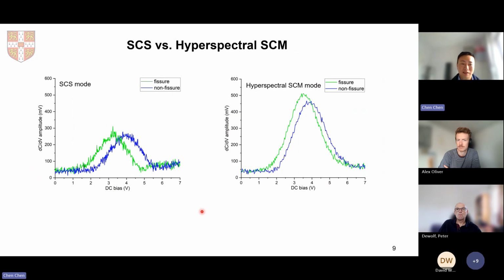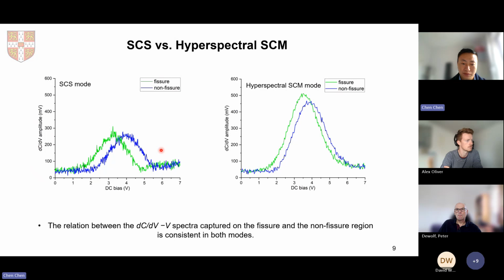We collected local dC/dV curves in two modes, SCS mode and also hyperspectral SCM mode. As you can see, in both cases, the fissure always shifts towards negative DC bias relative to the non-fissure curve. The relation between these two spectra, captured on the fissure and non-fissure regions, is consistent in both modes. If we look further, here I highlighted two DC bias values on the two shoulders of the peaks.